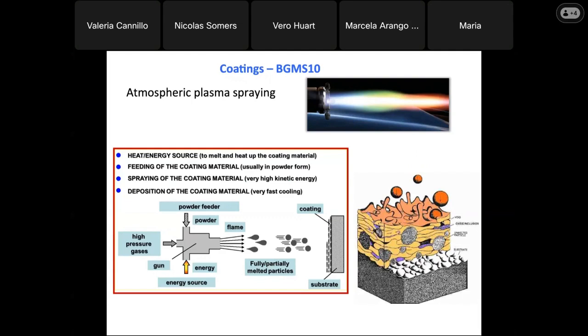Atmospheric plasma spraying is a technique in which you have a torch. The powder is injected in the torch. The bioactive glass powder melts inside the torch because the temperature is very, very high, like thousands of degrees Celsius. Then such molten particles are projected onto a substrate. During the flight, the particles cool down, and when they impact the substrate, they solidify, giving rise to lamella structures.